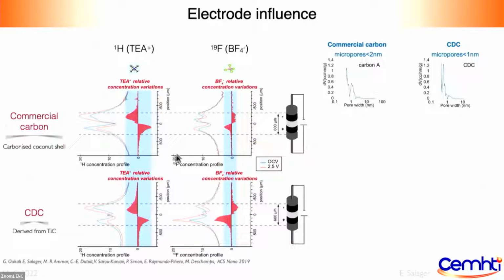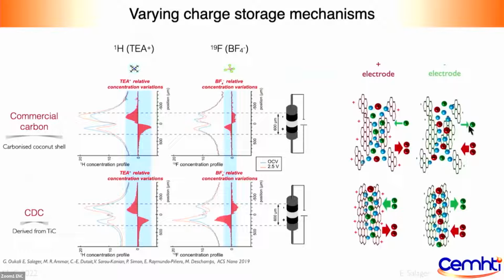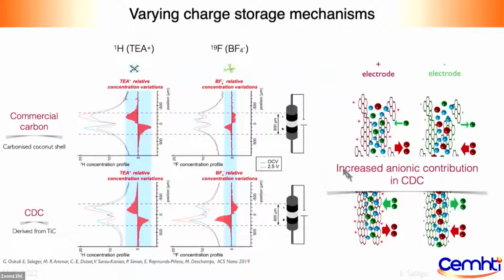And so then what we tried to do was to compare different types of carbon. So this is a commercial carbon, and this is a carbide-derived carbon. So it's chlorinated at high temperature to expel the titanium chloride, and we end up with a nanoporous carbon that has very, very tiny pores. And by doing so, we could identify that the fluorine anions did contribute a lot more in these carbons. And so this gave information on the mechanisms.